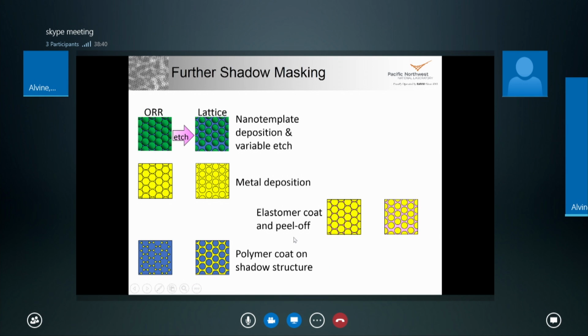You can take that a step further by controlling the etching of the material, you can create these bow tie type structures, and you can vary that essentially continuously between the bow tie type structures and the lattice structure. So with one deposition technique, you can make at least three different types of plasmonic structures. These all should be very well adaptable to large scale coating of things like windows.